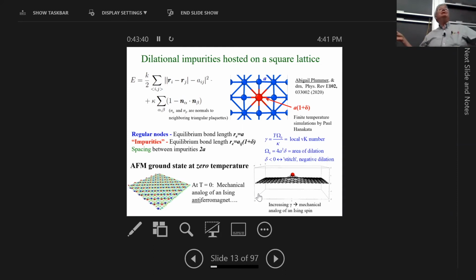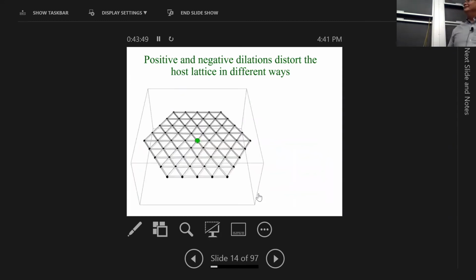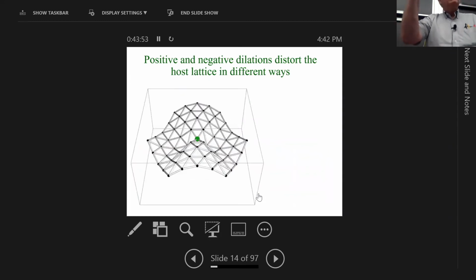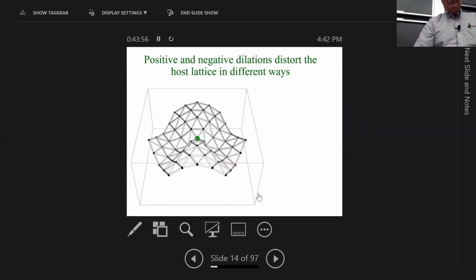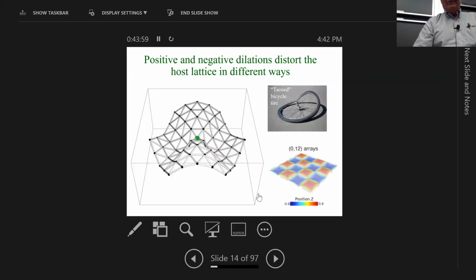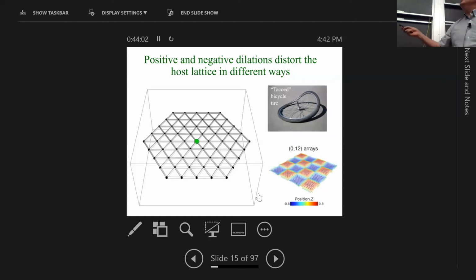So now the question is, what happens when we heat it up? Anything interesting happen when we mutilate this nice pristine lattice? This is negative bond shrinkage, negative dilation, that produces a kind of saddle. On many college campuses, you can see this in tacoed bicycle tires, because I presume what happens when it gets cold is these metal struts shorten more than the rim wants to shorten, and so it produces a saddle. And so you can have interacting tacos, if you like, which also seem to form an antiferromagnet.